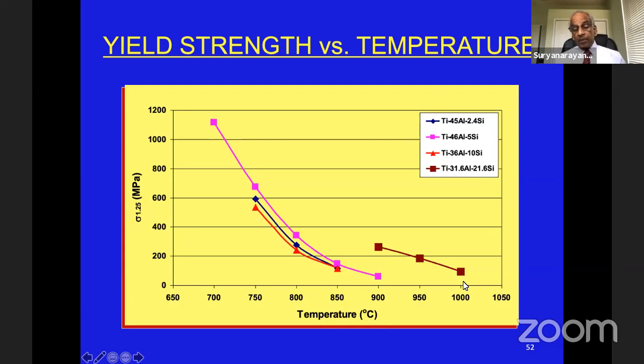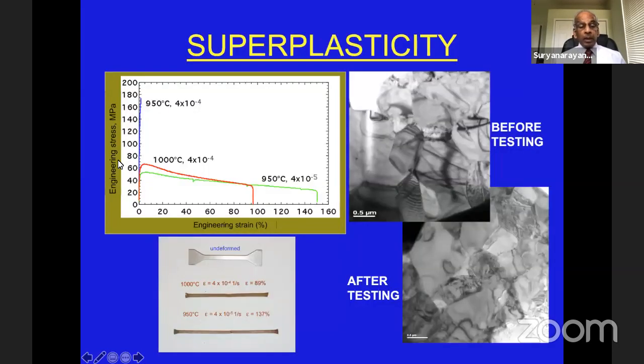It decreases even up to 1000 degrees Celsius. Now, you can do the stress strain test on this material at different strain rates and at different temperatures. At 950 degrees, 10 to the power of minus 4, you would see almost like elastic deformation only. But if you decrease the strain rate to 10 to the power